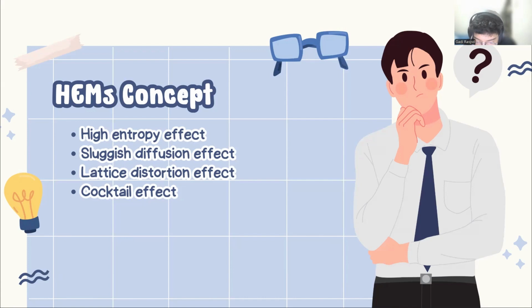The slow diffusion effect is marked by decreased atomic mobility within the high entropy matrix, influencing photocatalysis in various ways, such as defect creation and prevention of particle agglomeration. This lower diffusion rate can result in the emergence of non-equilibrium defects and vacancies, which may act as active sites for photocatalytic reactions. Furthermore, the slow diffusion process helps to preserve the dispersion of nanoparticles, avoiding clumping and maintaining a high surface area, which is beneficial for active photocatalysis.